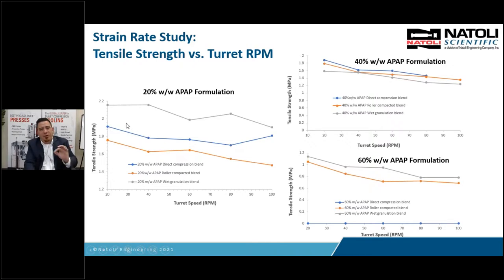So I'm not really focused on which one has the highest tensile strength here. I'm focused on the drop from the start to the end. And that is evaluating our strain rate sensitivity. So we can compress tablets all day at low speed on R&D and make robust tablets. But when we go to a high-speed manufacturing press and they're hitting so fast and the dwell times are so low, that might cause a weaker tablet. That can cause capping issues, because if your material is strain rate sensitive, you're going to have weaker tablets at higher speed.